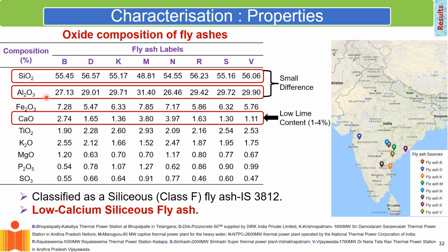The other thing we also notice is that in most Indian fly ashes, the lime content is very, very low. So coming back to the substitution, if you remember, if I'm going to use fly ash in cement, I bring in silica, but that is also questionable because, I don't know, something is not really correct about this picture here.